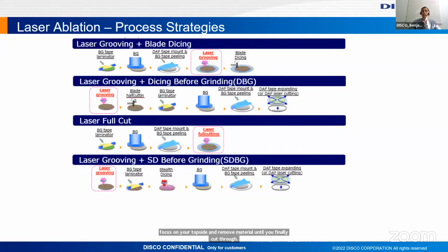Another approach, where you see there are quite a lot of synergies between laser grooving and different approaches, is stealth dicing before grinding. More or less you do the stealth dicing modification from the backside. But if you have on the pattern side some metals that are hard to expand, then you need to remove them also with the laser.